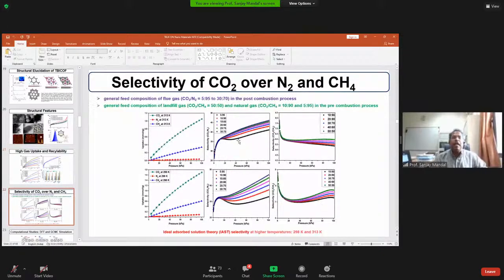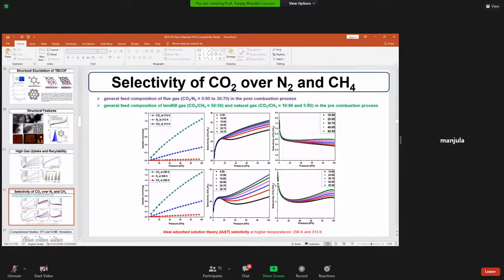Based on this data, we looked at 2 things. One is because the flue gas has carbon dioxide to nitrogen of 5 to 95 to 30 to 70 after post-combustion, and landfill gas has CO2 to CH4 at 50-50, and natural gas has CO2 to CH4 10 to 90 to 5 to 95. That's why we have to have selectivity at this ratio.